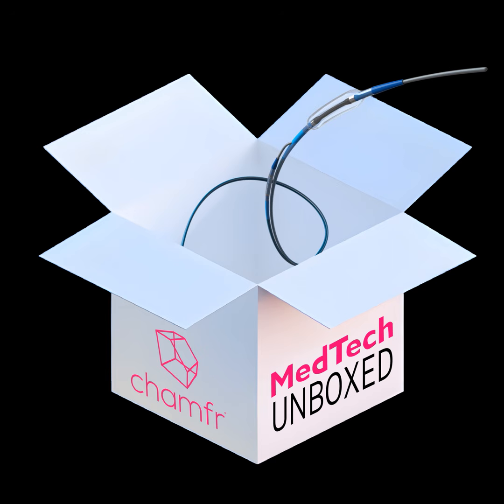And you mentioned delamination. I might be wrong, but I think the biggest recalls on catheters are related to delamination. So that's a big issue. The etching is another step, and I think the etching has a shelf life. One of the solutions to that is the tie layer. It locks in the etch, but also gives you some additional bonding, which is really cool technology actually, to add such an ultra thin coating over a PTFE, whether it's extruded or film cast, to increase bonding. That's great technology, but if you can avoid a step in the process, you're going to be more efficient, right? Yeah, yeah.